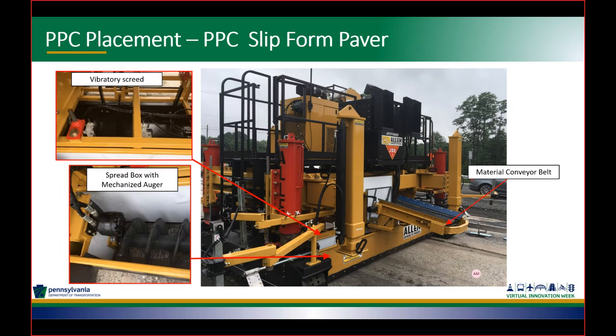But for high production rate, or if you go very thick, I'm talking 2 inches plus, 3, up to 6, 8 inches thick, even more, you are looking at using a slip form paver. So this is manufactured specifically for polyester polymer concrete.